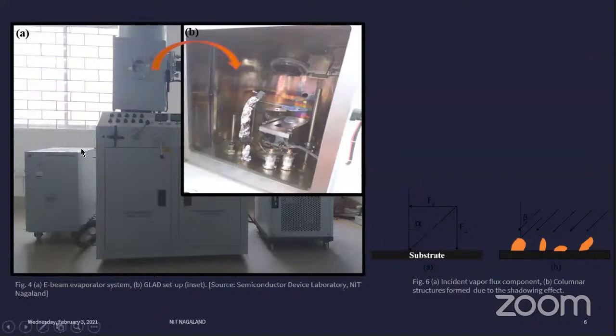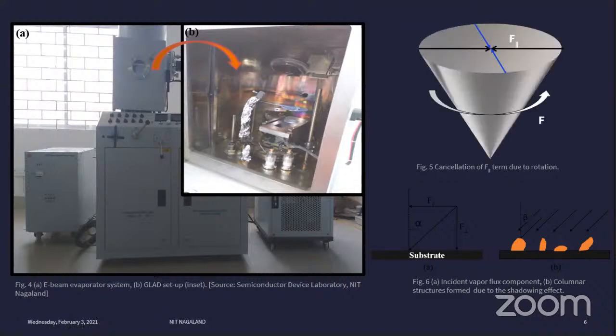So this is the experimental apparatus, the e-beam evaporator system, wherein in the inset you see the chamber where the deposition takes place. The deposition is carried out at a high vacuum pressure level, and the mechanism as to how we can achieve vertical nanowire is that the incoming vapor flux, after the source has been evaporated, can be divided into two vector components. One is the perpendicular component and the other one is the parallel component. Since in the GLAD technique we are rotating our substrate, due to the rotation the parallel component gets cancelled out, and effectively we are left with the perpendicular component. Hence, we can achieve perpendicular nanowires comparatively easily with other techniques.